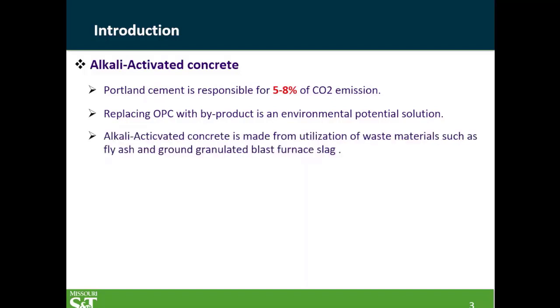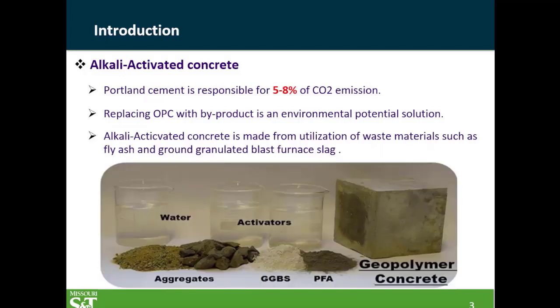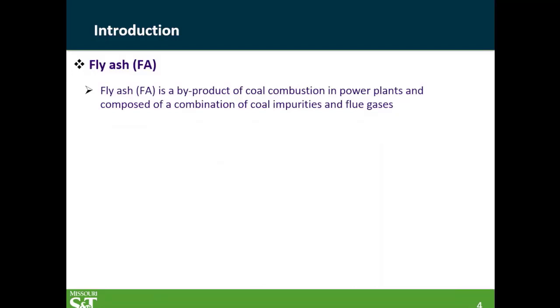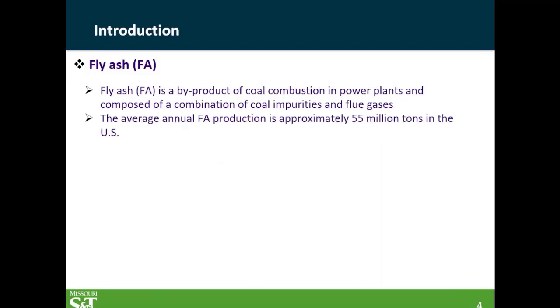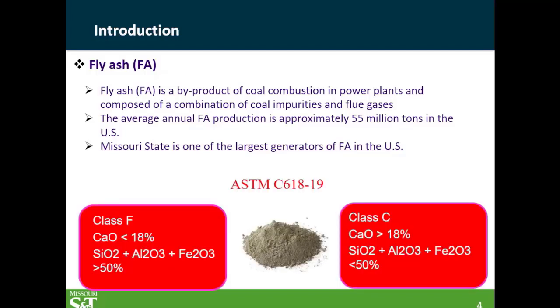We are looking at alkali activated concrete, where we use a waste material such as fly ash or slag, and then activate it using alkali solutions. The alkali solution that we are using is sodium silicate and sodium hydroxide. Fly ash is a byproduct material. In Missouri, we have one of the largest coal power plants in the state, so we have plenty of fly ash in the state.